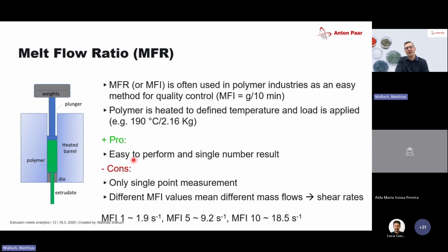Because if I have different MFI values, I get different shear rates. So for example, if I have an MFI of 1, the shear rate applied in the nozzle is about 2 reciprocal seconds. Whereas when I'm having an MFI of 5, for example, it's approximately 10 reciprocal seconds. So we are looking at a different spot on the viscosity curve. And we have no clue how my material behaves at the real conditions in my process. So this is a huge drawback.